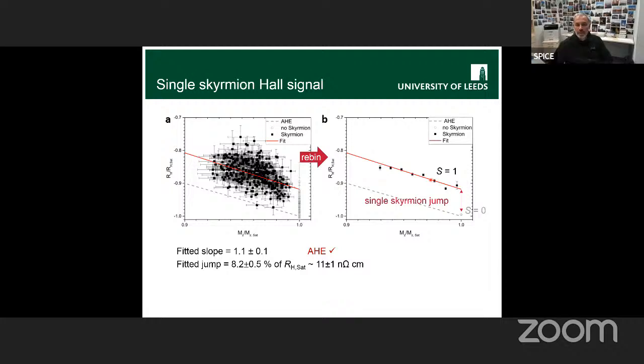So the slope of this line you can explain just through the anomalous Hall effect. But then at the end, when the skyrmion is annihilated, you get this jump. That's the size-independent part. The size-dependent part, as you move up and down the slope of this line, is totally consistent with what you'd expect from the anomalous Hall signal. But there's this jump, which is not. If all you had was an anomalous Hall effect, you would just go up and down this gray line, which has a slope of -1, with the Hall signal proportional to the Z component of magnetization. So the size-independent part is this jump, which corresponds to this change in topology, and that's the bit that needs further explanation.